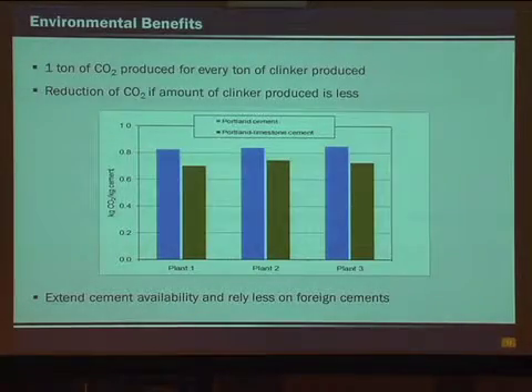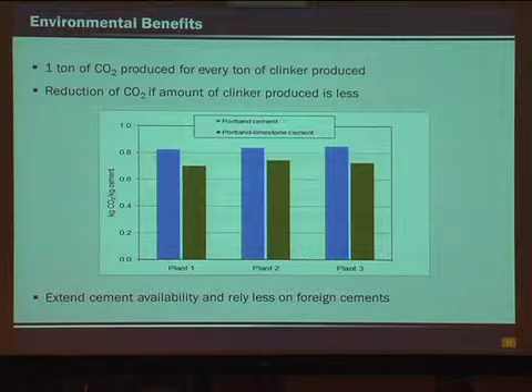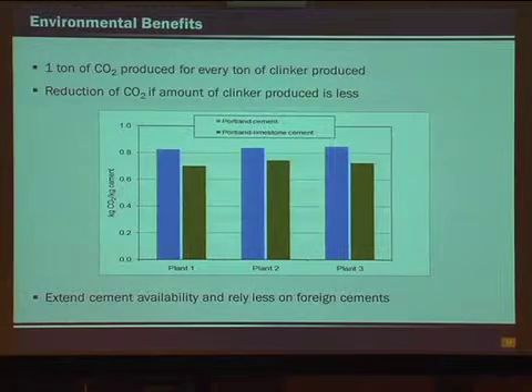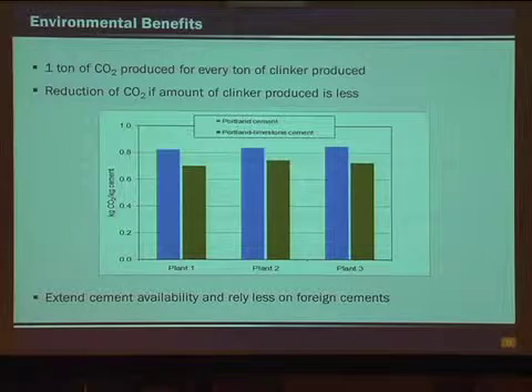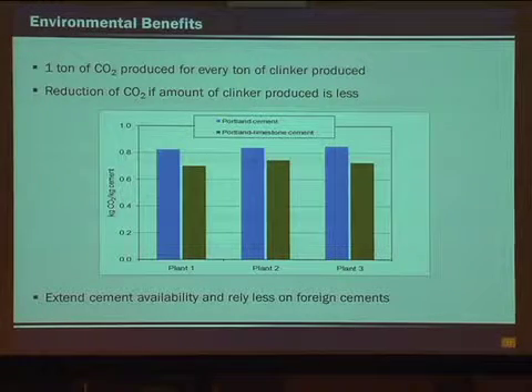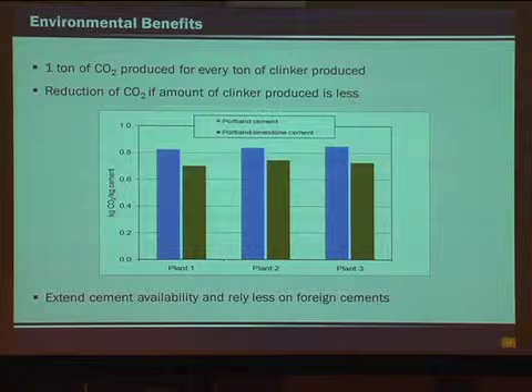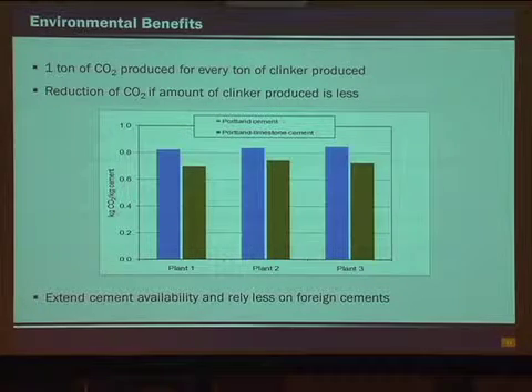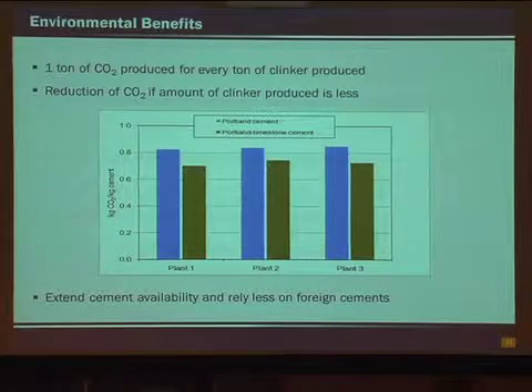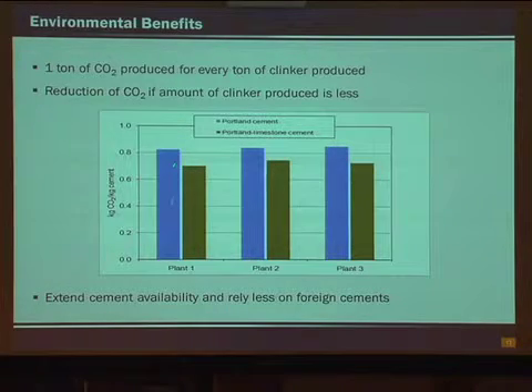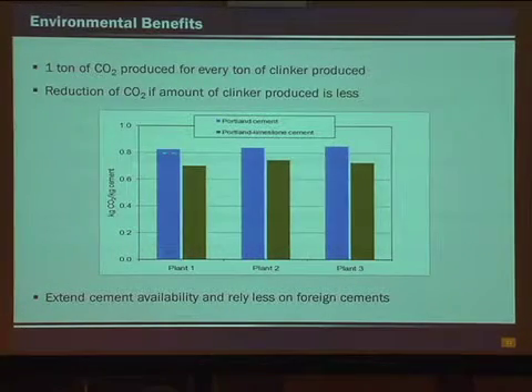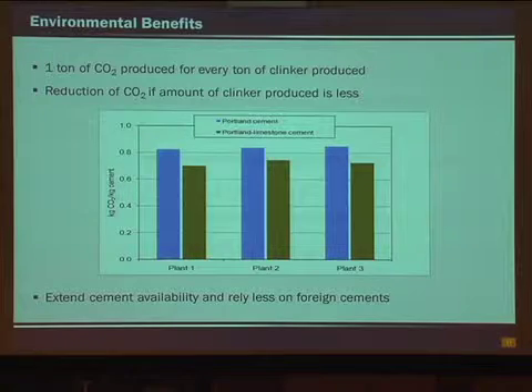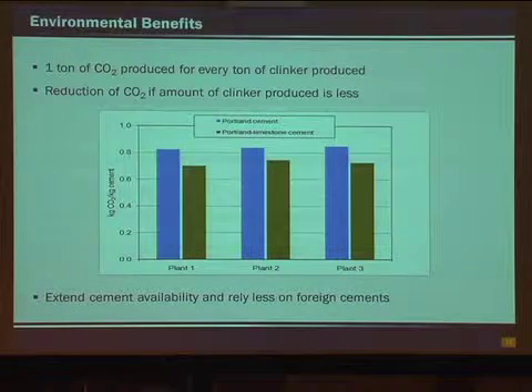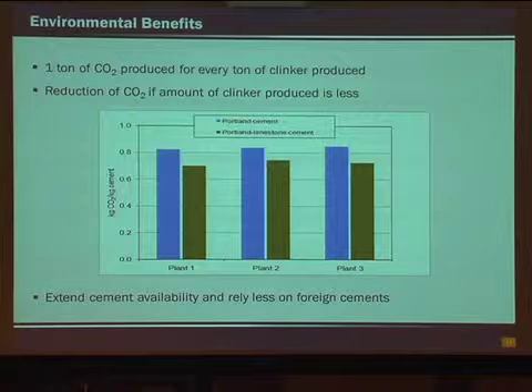All right, so environmental benefits. As everyone knows, for every ton of clinker you produce about 1 ton of CO2. So if we're producing 15% less clinker because we could put 15% limestone in, then we should see a reduction of 15% CO2 production in cement plants. And here's just a plot showing just that. Base cement, limestone cement, and you see the reduction of CO2. Plain and simple. Don't make 15% of it, you should get a 15% reduction.